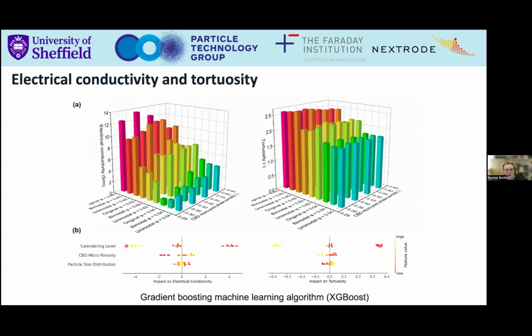So by doing a machine learning analysis, and we use a gradient boosting machine learning algorithm called XGBoost, we're able to see what all the relative contributions to the performance of our electrodes are. So for example, here we're looking at the impact on the electroconductivity. On the right, we're looking at the impact on tortuosity. What we found was that the calendaring level by far had the largest impact on our conductivity.